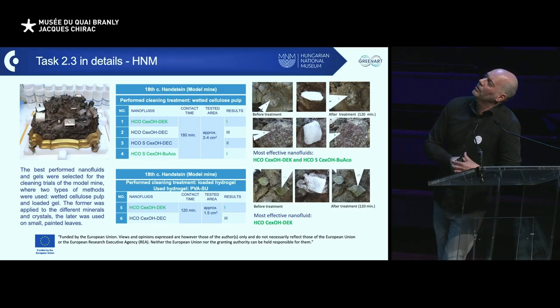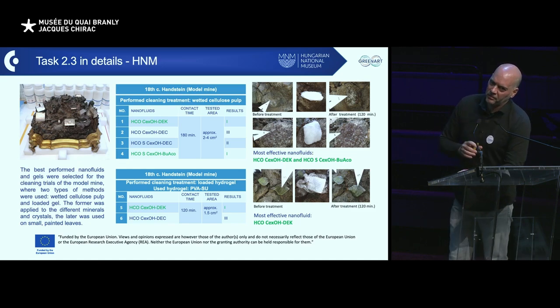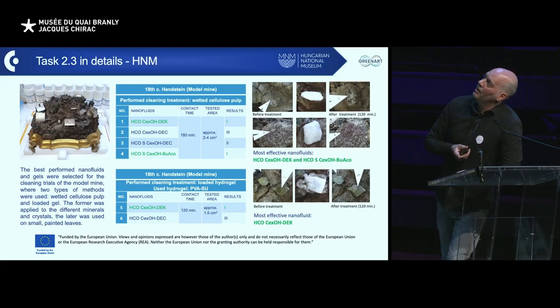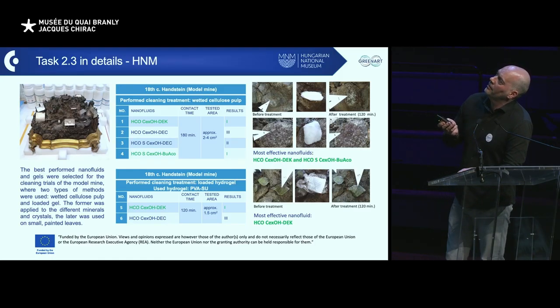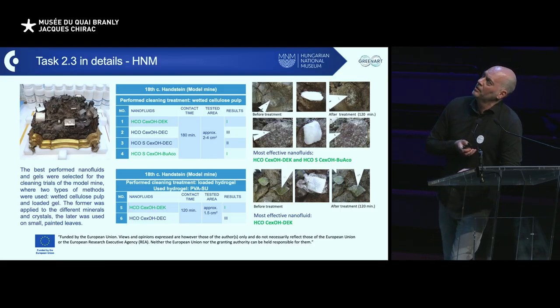In the case of the Handstein, because I told you there are crystals and minerals on the surface, glued originally with animal glue, but afterwards it was repaired with several different materials anyway. So we had very complex structures. For example, on the surface of the crystals, we used the cellulose pulp, a type of cleaning method. We put cellulose powder into a Japanese paper and then wetted this kind of pad, and pushed it onto the surface. And as you can see, I hope you can see, it was effective. On the surface, there was a kind of whitish contamination, and after the treatment, it showed a very nice result, and it's very promising. And in this case, the diethyl carbonate and the butyl acetate showed very nice results.